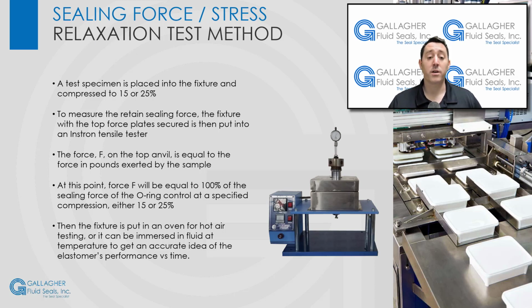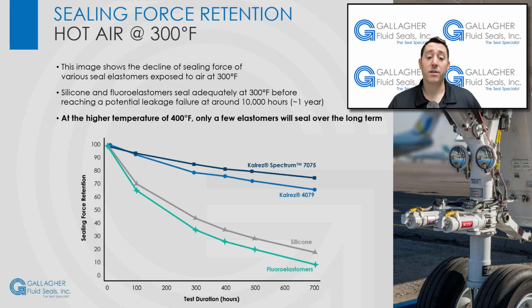Then the fixture is put in an oven for hot air testing, or it can be immersed in fluids at temperature to get an accurate idea of the elastomer's performance versus time. This shows the decline of sealing force of various common seal elastomers exposed to air at 300 degrees Fahrenheit. Silicone and fluoroelastomers seal adequately at 300 degrees Fahrenheit before reaching a potential leakage failure at around 10,000 hours. This test provides a relative comparison only, since actual sealing performance is dependent on many other factors, and service life may be less than indicated in this test.